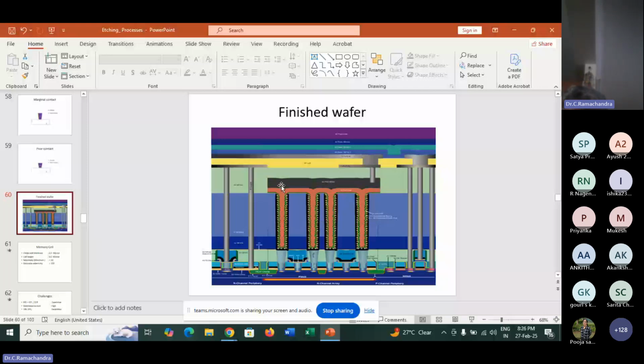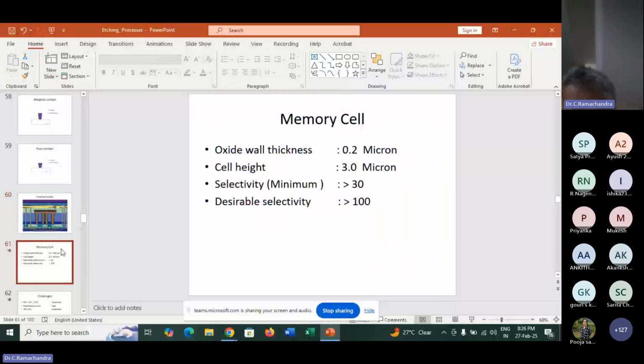There are so many silicon layers. So when I am trying to remove this and reach the polyplug, even the substrate may get damaged. So controlled removal of this polyplug and all these so many other layers is very, very challenging, and we were successful in developing it. For example, if you consider a memory cell, the oxide wall thickness is less than 0.2 micron, the